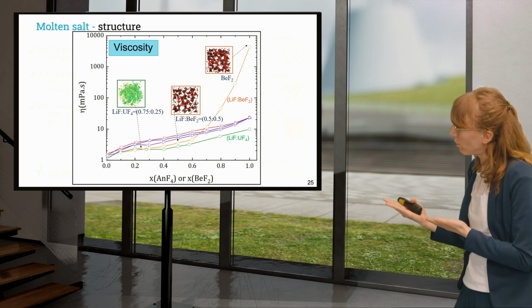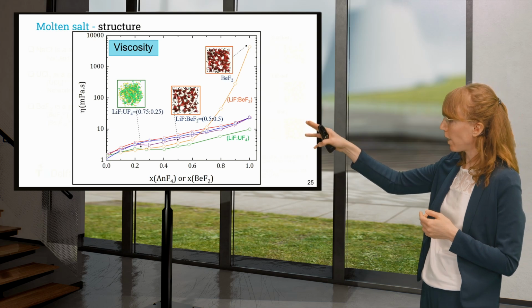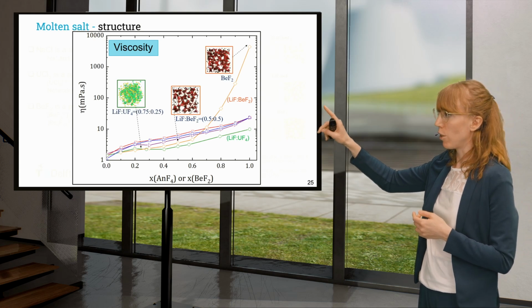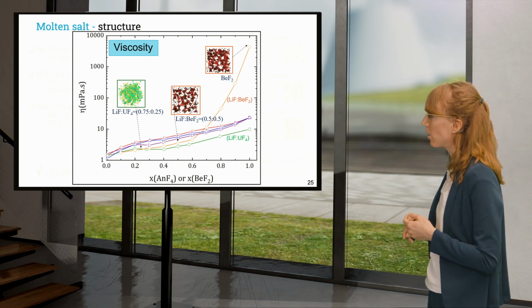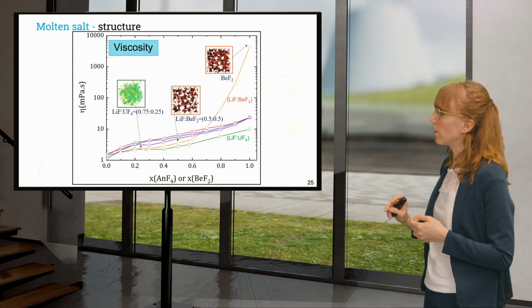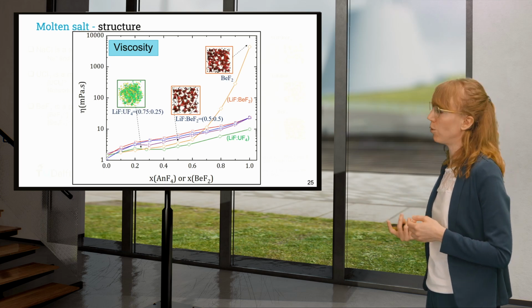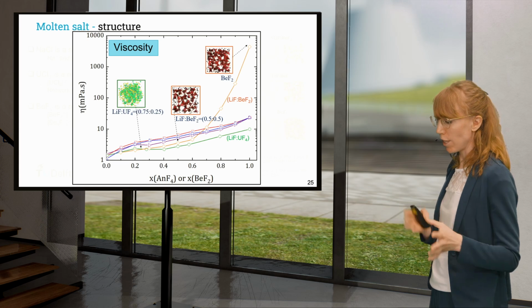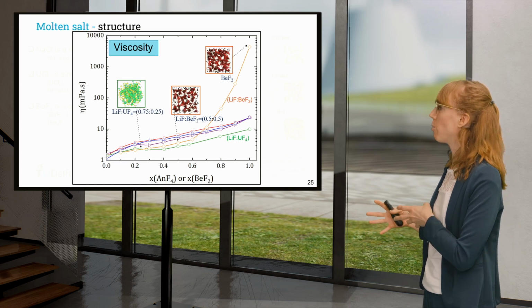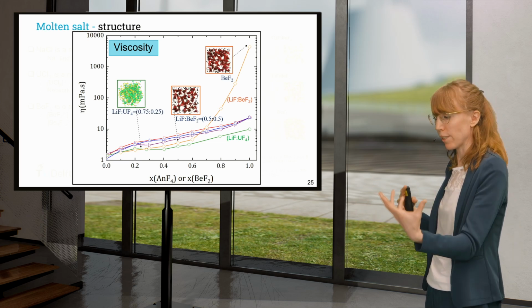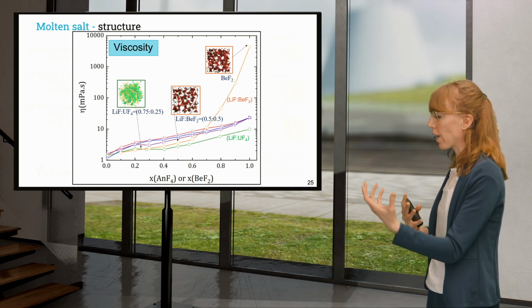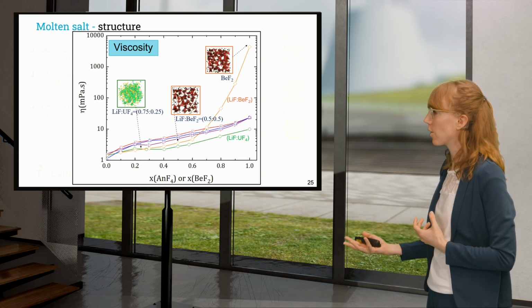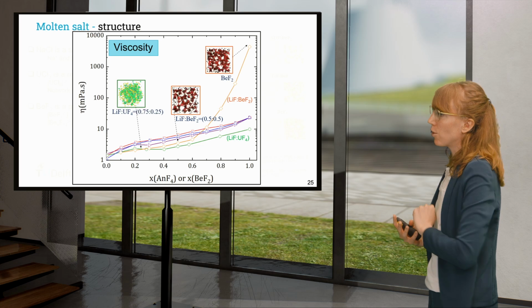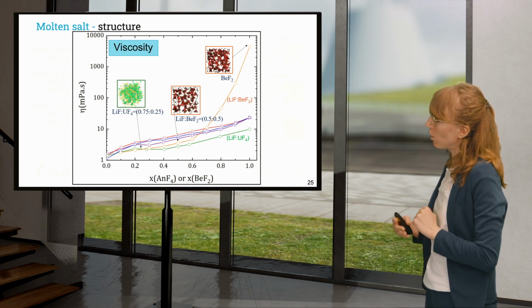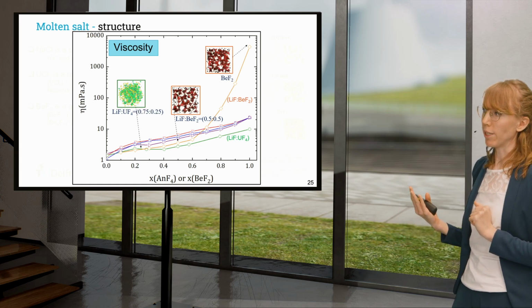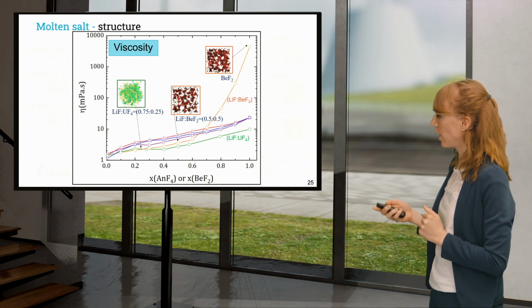If we take the example of viscosity, we can see here in orange the viscosity of a lithium-beryllium fluoride mixture, and you see that this viscosity increases by 4 orders of magnitude between lithium fluoride and pure beryllium fluoride. So that shows the direct link between structure and viscosity. In the case of the lithium-uranium fluoride mixture, we have an increase of 1 order of magnitude. Still something we need to consider.